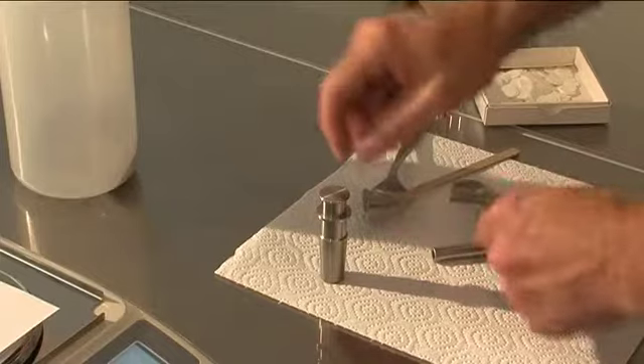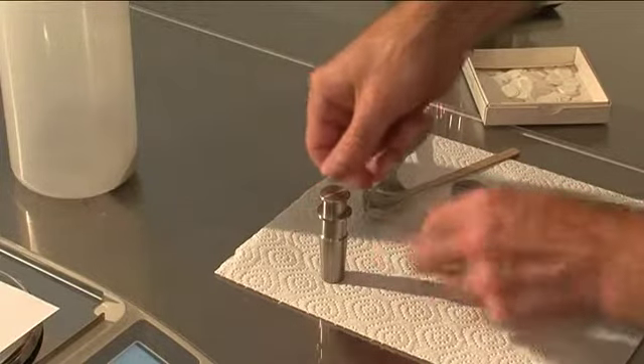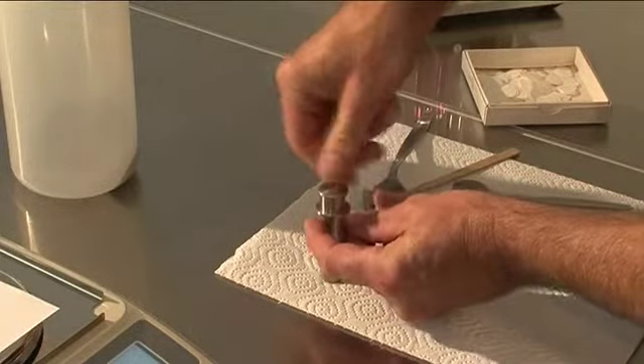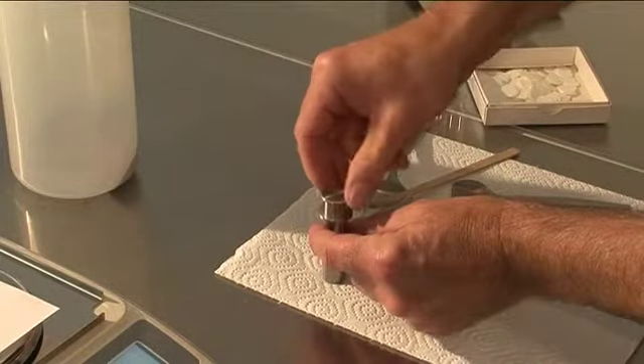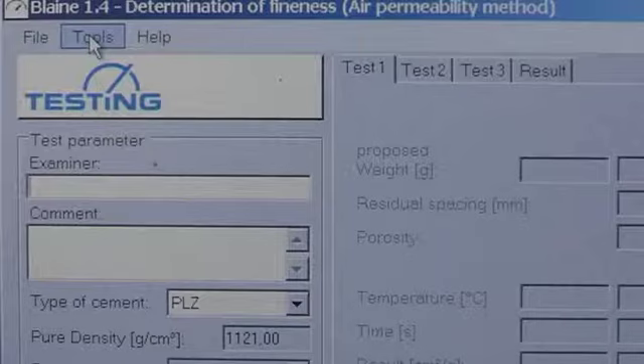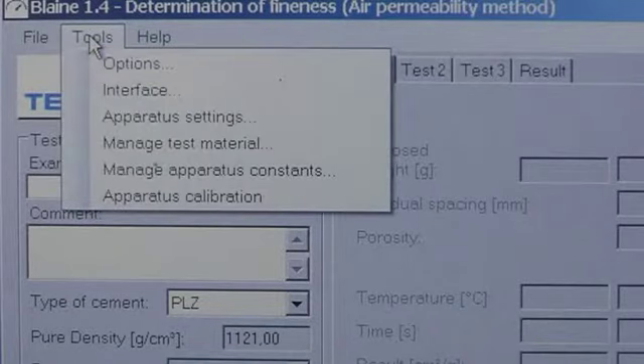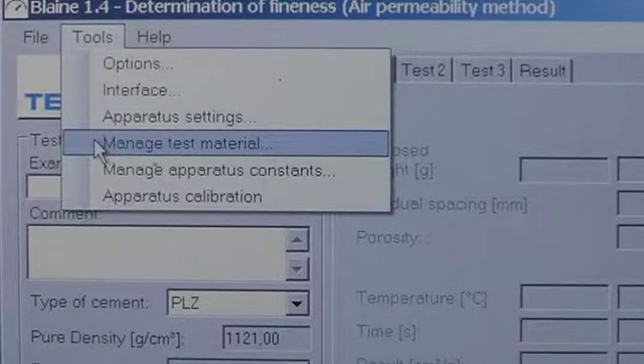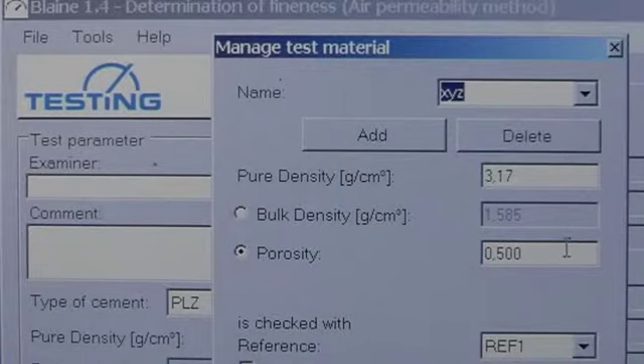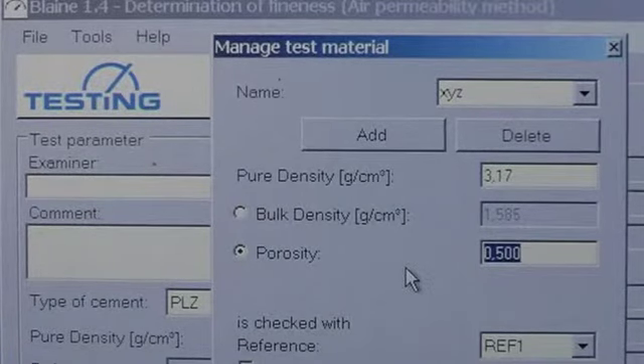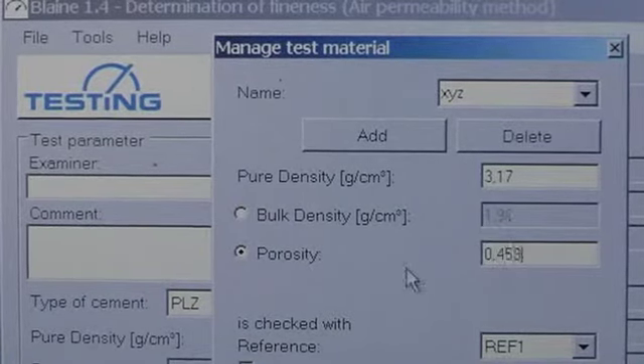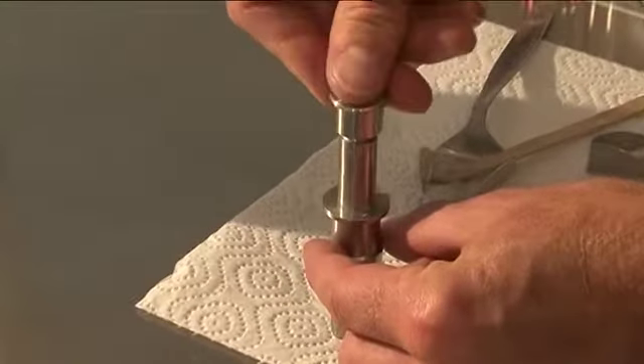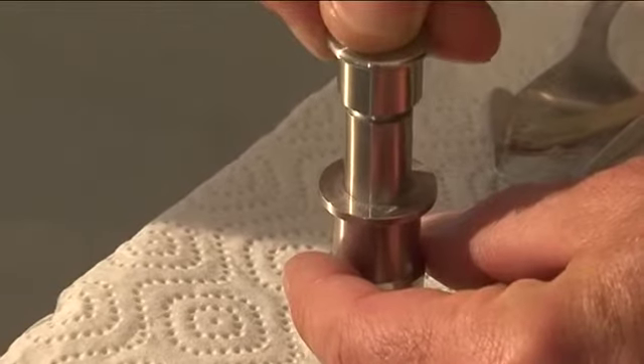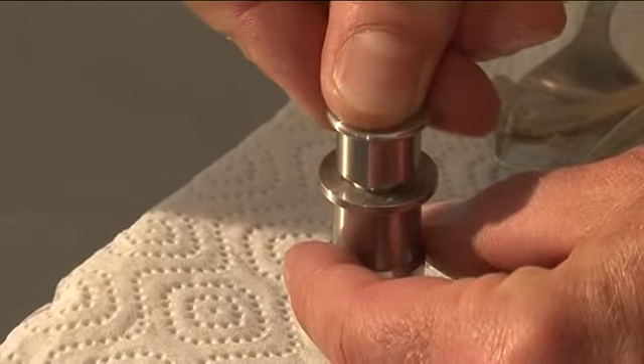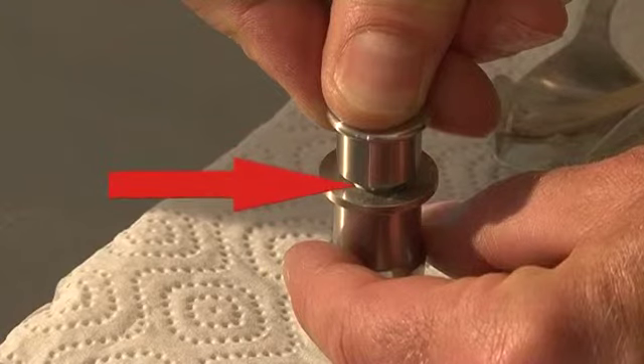Should the plunger not reach the cement bed due to insufficient weight, a new calculation must be carried out with a new suitable porosity. Return to menu item Tools, Manage Test Material and recalculate the sample weight by changing the value of the porosity. If the plunger collar doesn't reach the measuring cell edge because of too much weight, recalculate with a new porosity.